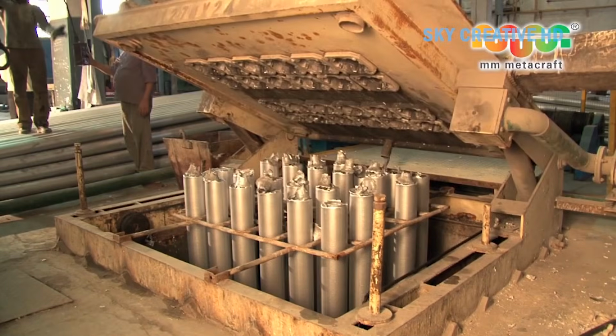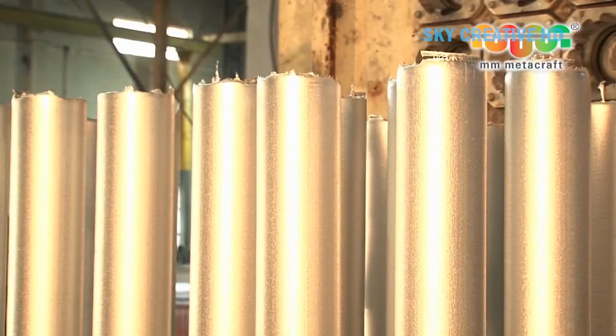Too cold and the press force spikes, risking die damage. Too hot and the metal loses structural integrity, leading to surface defects and profile distortion. The furnace heats the billet with a temperature gradient, slightly hotter at the back end, to compensate for the cooling that happens as the leading edge of the billet contacts the cooler press components.